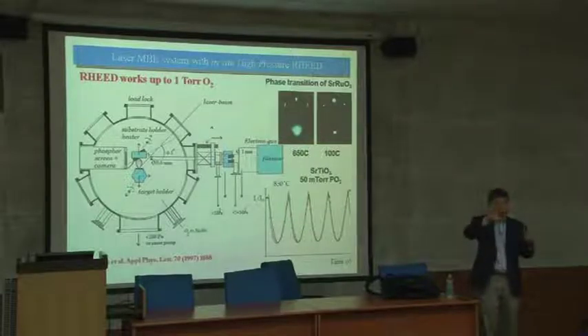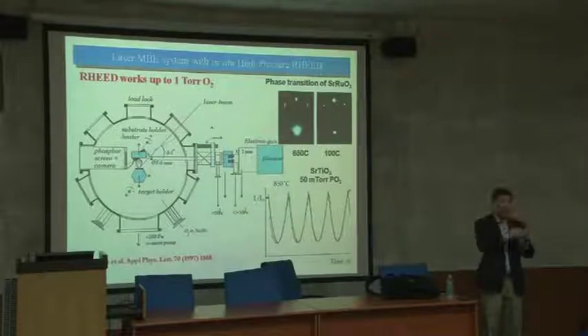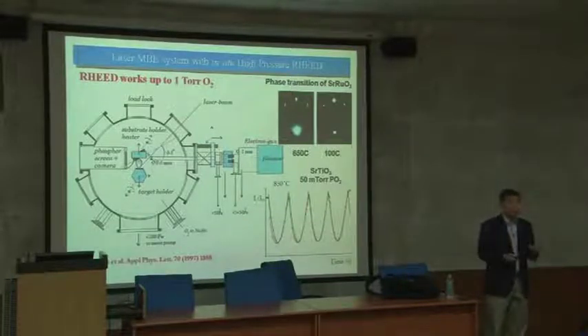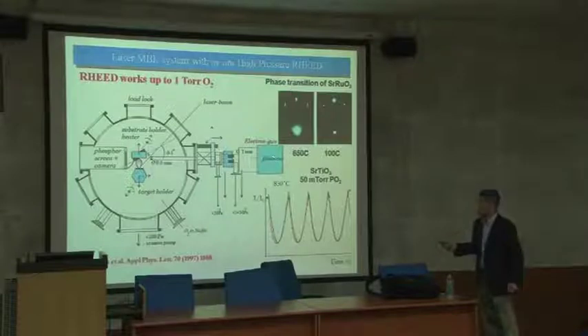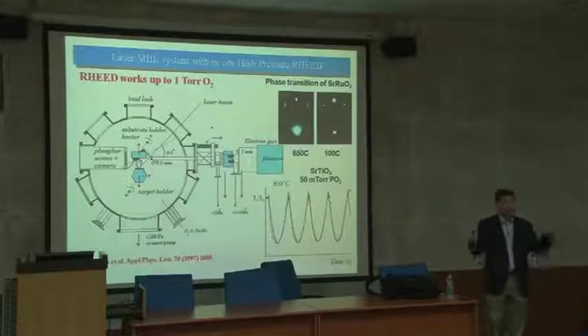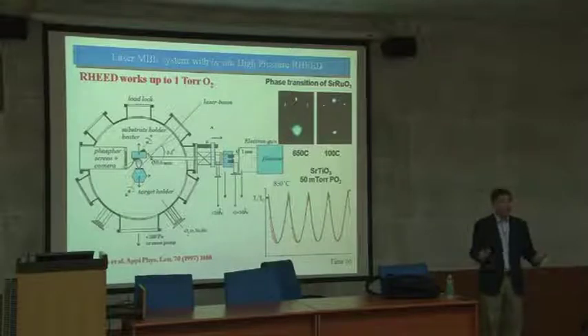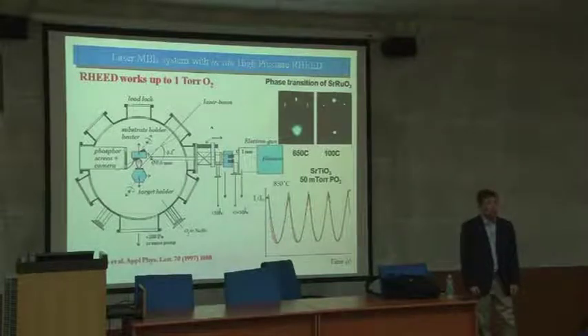And using some coils outside, you bend the electrons and focus the electrons, and that's basically what you do in an electron gun. And then you have a tungsten filament at very high temperature, and you have oxygen, then what happens? It burns the filament. So you don't want to have any oxygen on the filament side. But on the vacuum chamber side, I need a lot of oxygen. Then how do you actually do those two things?